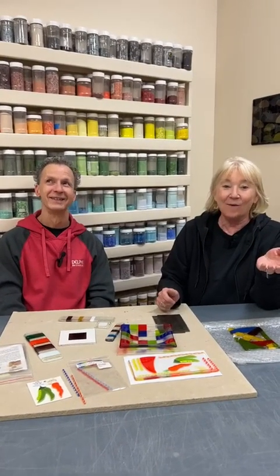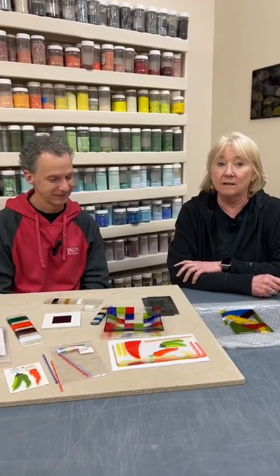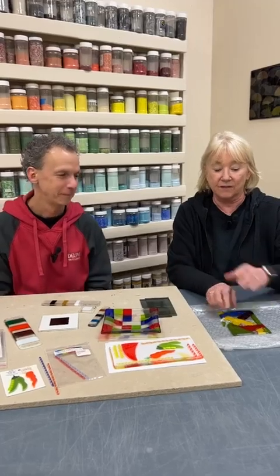No, you can't. If this were a temperature issue, and it was just a straight crack, and we put it together and somehow fused it again, we could get away with that. We would be fixing the problem because that was a temperature issue. But you can't keep firing an issue that's incompatible. It'll just keep being incompatible, and it'll just keep re-breaking. So it might melt back together, but it will also start cracking again. If you've got something like this, just save it and show people. That's an example of what not to do.